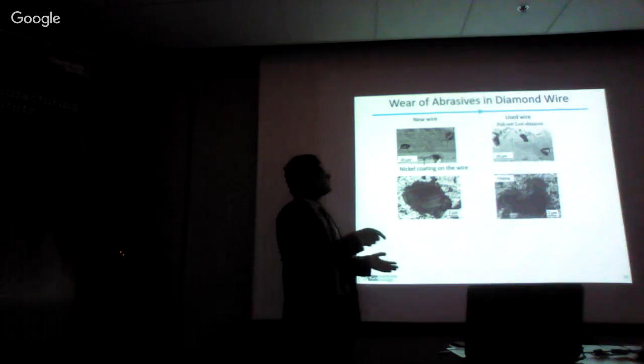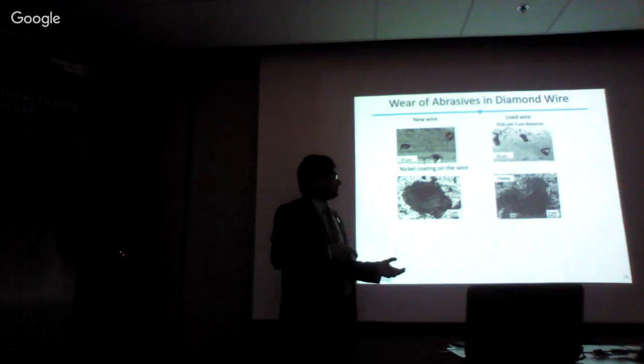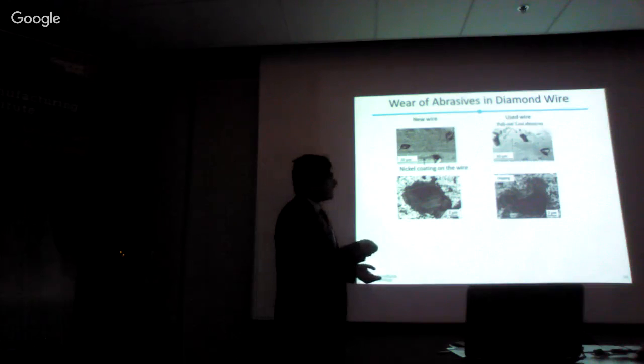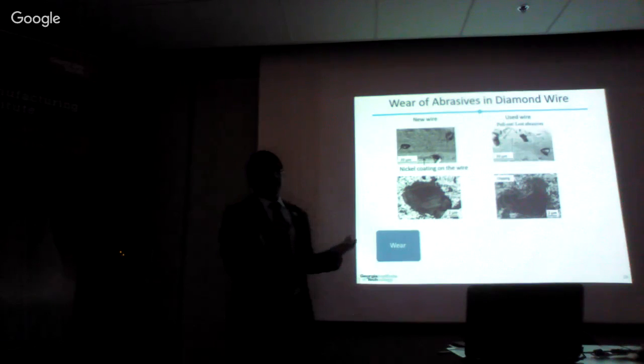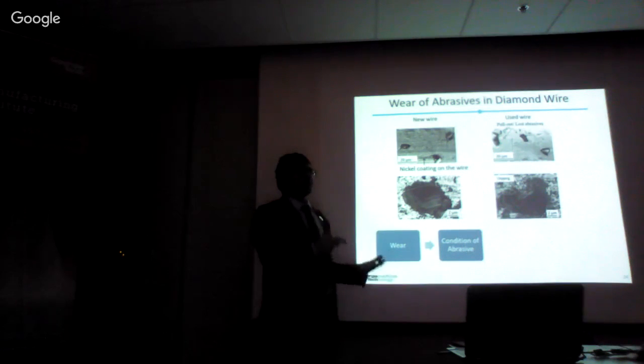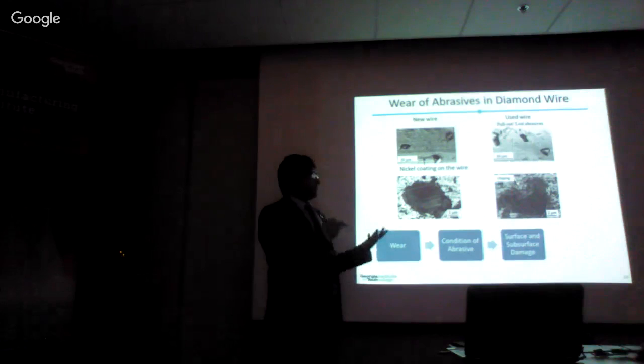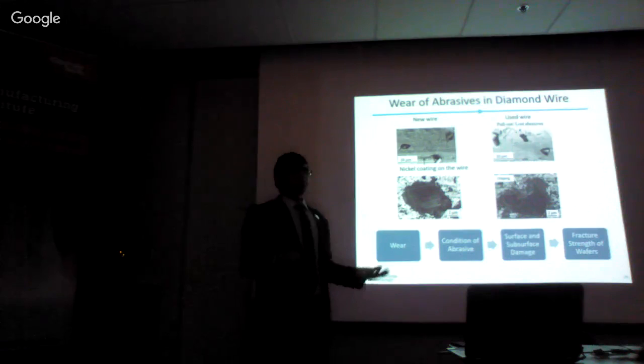Compared to that, on the used wire side, we found some of the abrasives are missing, or lost because they are pulled out during the cutting process. Some of the abrasives have chipped off, as you see here, this fractured diamond. This means that the wear of the abrasive affects its condition, which will in turn affect the surface and subsurface damage of the silicon wafers it is cutting, and that in turn will affect the fracture strength of the wafers, which is what we find in the next few slides.